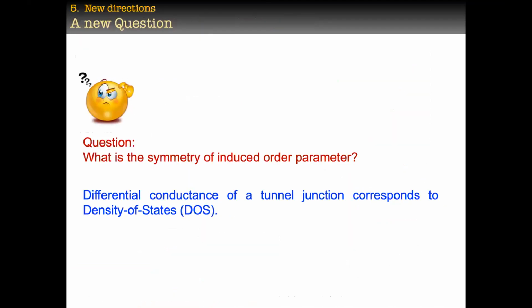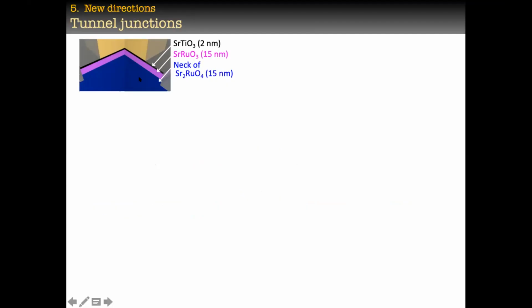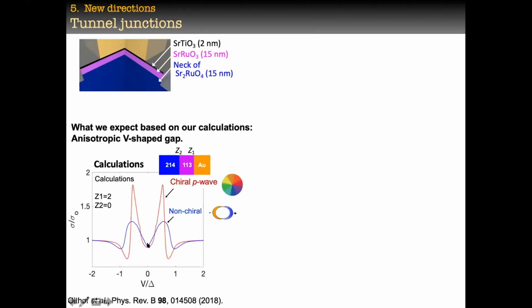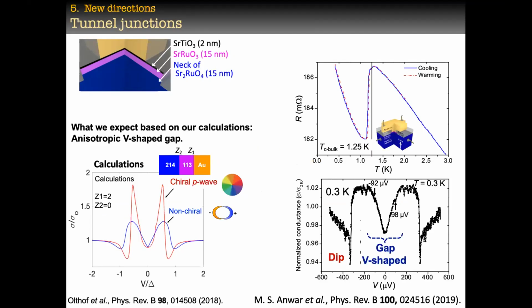So now you can ask the question of what kind of order parameter it is. I would not spend much time over here because it will be a little bit difficult for you guys, so I would like to make it as simple as possible. The order parameter means the density of states, that is, how the density of states looks. Because as I said, S wave, P wave, D wave order parameters, those we can see with the differential conductance. So with that idea, what I did, I put a barrier between the top gold electrode and the ferromagnet. So now you can measure the density of states because this is a tunnel junction. We did the calculations and we found that our conductance must be V-shaped. V-shaped means that it should be the P wave order parameter and spin triplet.